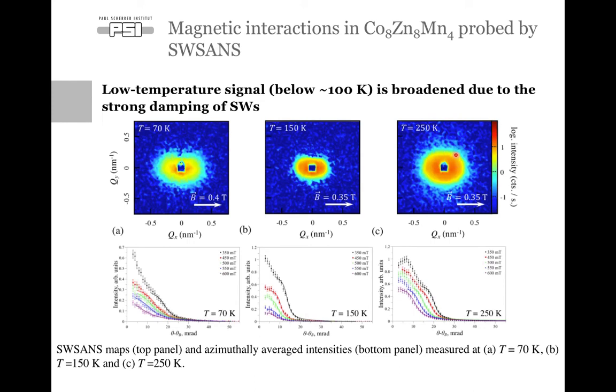And interestingly, we can see a very clear spin wave scattering signal. Now I show you the results that we have obtained with non-polarized neutrons. So there's no difference between left and right, but we can still extract the spin wave information without losing anything. And we can clearly see the spin wave scattering at 250K here, for example, around 150K. But as we cool down more, the spin wave scattering intensity gets much weaker, and the distribution gets much broader. So it's getting quite difficult to distinguish between